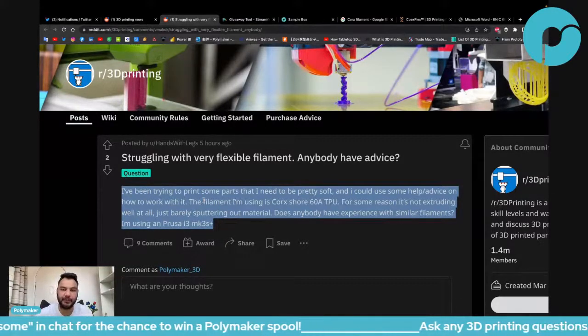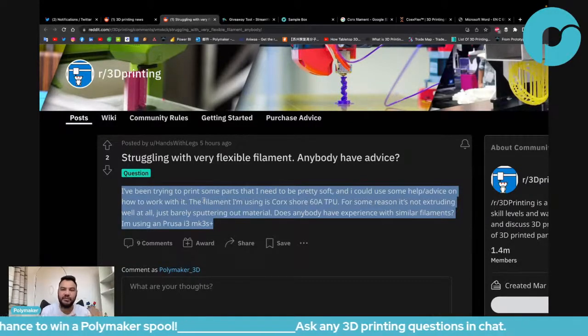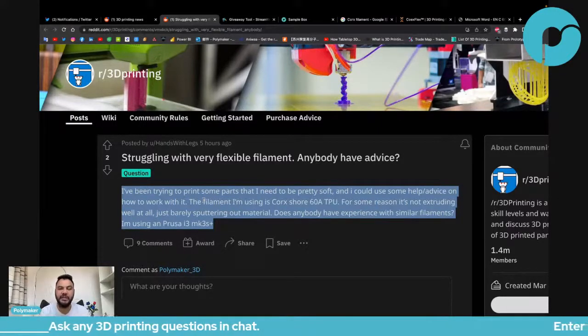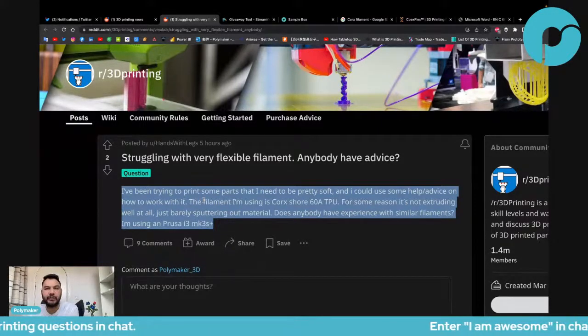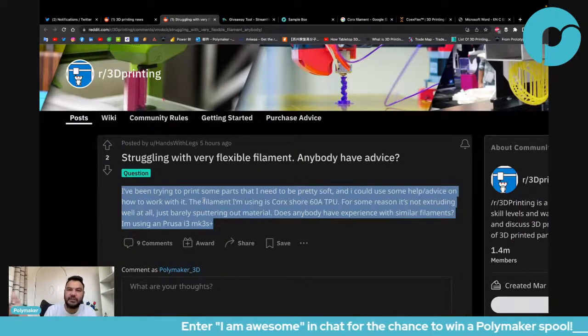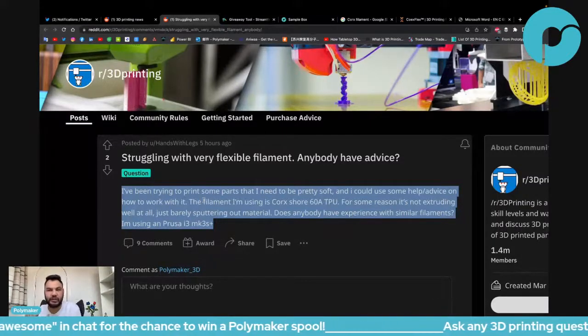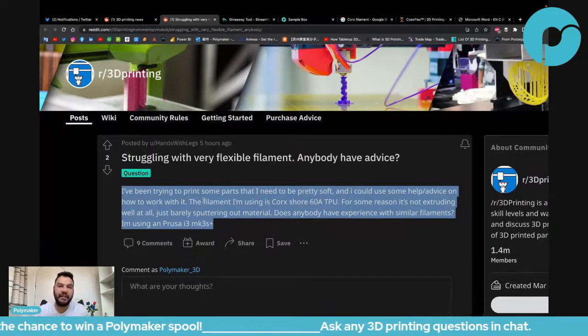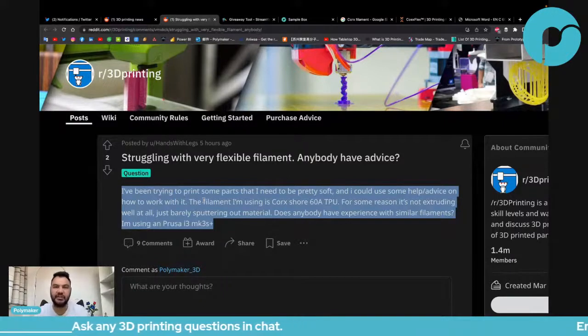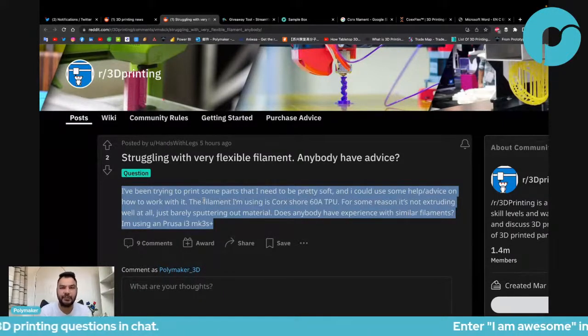The Shore hardness is very useful for injection molding because it's 100% infill anyway, so the only softness you get is from the material. But in 3D printing, it's completely different. You can have a model that is softer than another one, even though this is a rigid material and this is a flexible material, because it all depends on the structure. The flexibility in 3D printing depends as much on the structure as it depends on the material. In injection molding, it mainly depends on the material.